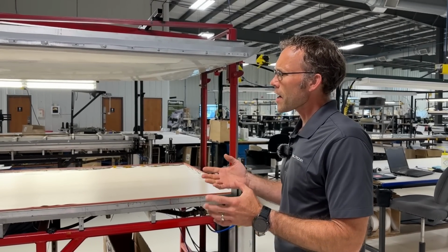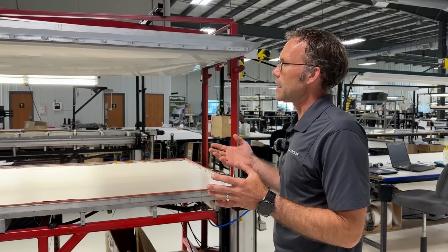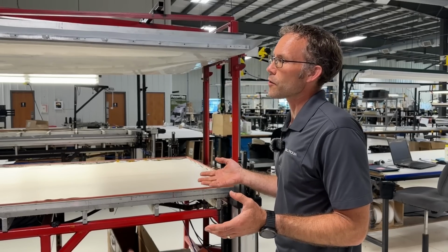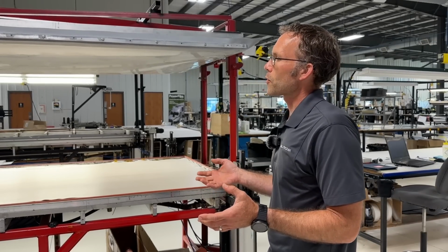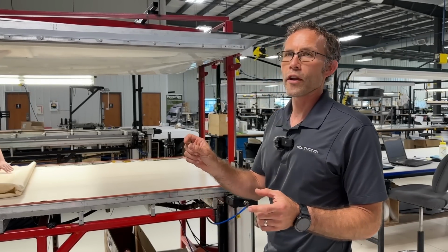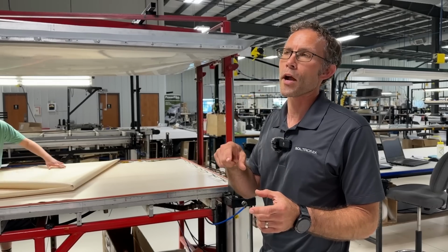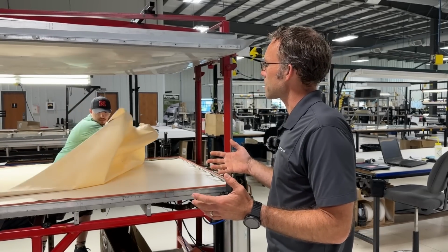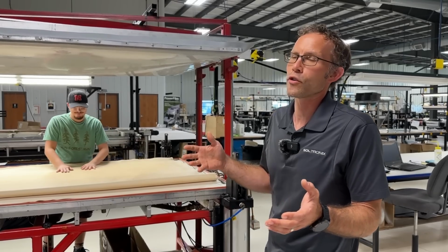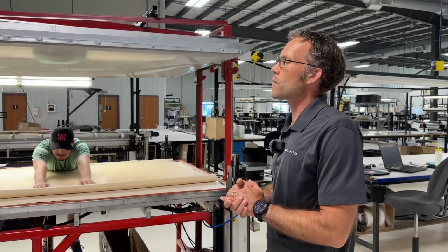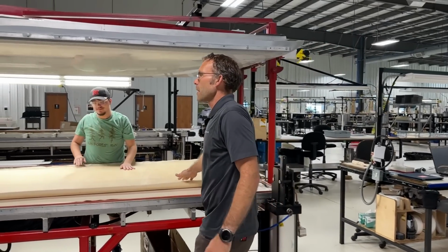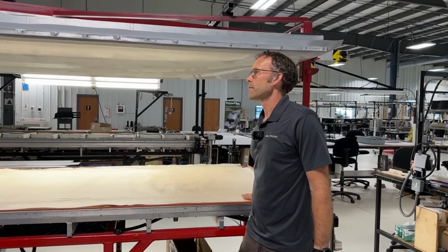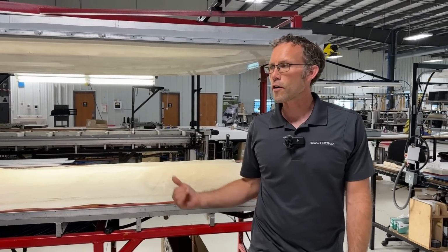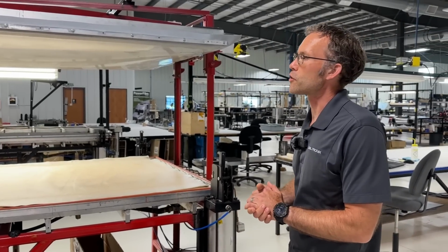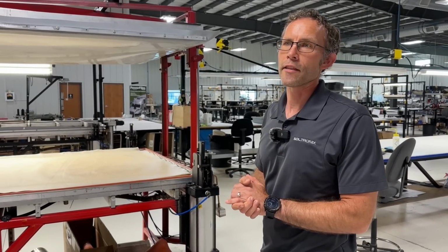The vacuum lamination is much slower than the roll lamination that we have for the foldables, but it provides a 1/4 inch to a 1/2 inch seal around the whole product, which basically encases it so that no matter what you do, you're not going to get moisture in there. We've got panels that actually get run underwater. And so the panels that are used underwater use this type of thing, and there's no issues with running them in salt water or anything long term.